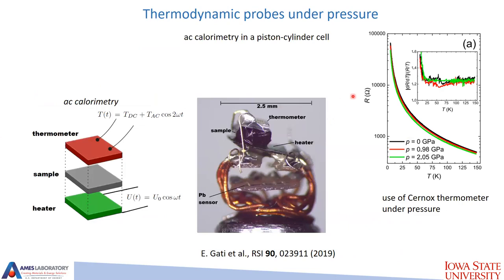So, which thermodynamic probes will we use? First, it's AC calorimetry in a piston cylinder cell. The technique is somewhat known. Here, we were using a Cernox thermometer under pressure, which gave us a significantly larger temperature range than many previous works where AC calorimetry was done under pressure.